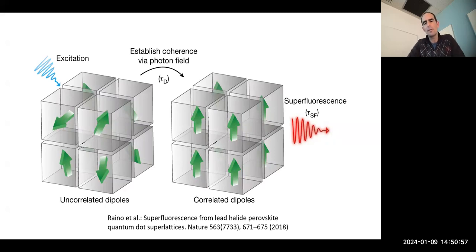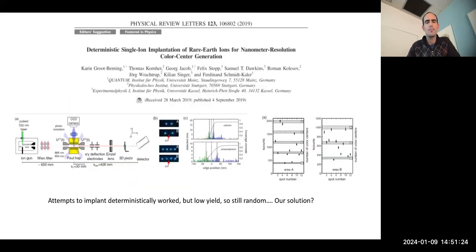Yeah, so that is critical for these rare earths. If you're not looking at the radioactive properties, but just looking at regular visible and near infrared emission, you do want to have the implantation larger than 1 or 2 nanometers, for this quenching property. I think this is not the case here, where they implanted in this crystal — I forget which crystal they used, maybe it was yttrium vanadate or something. But yeah, they weren't able to — they were getting quenching, so obviously they didn't have the level of control that would be beneficial in this case.